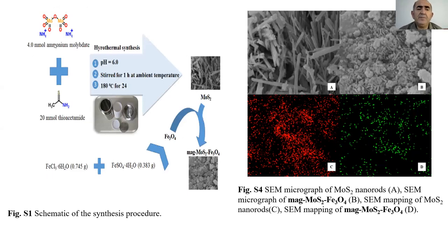We used ammonium molybdate plus thioacetamide at pH 6, and after suitable pH, suitable pressure and suitable temperature, we get these materials. The characterization of these materials is important. As you know, we used scanning electron microscopy in the characterization steps.